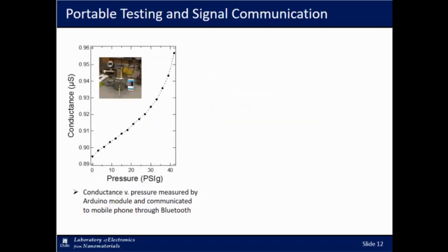So from here, we designed a proof of concept test just to show that we could measure this signal and transmit this signal using an Arduino, a low-cost Arduino and Bluetooth module. So we designed a simple voltage divider circuit with our transistor as one element, and we measured the conductance of the carbon nanotube thin film at a specific gate source voltage and drain source voltage, and correlated that to pressure. So the whole design fit inside the pressure chamber and communicated the data back out to a cell phone.